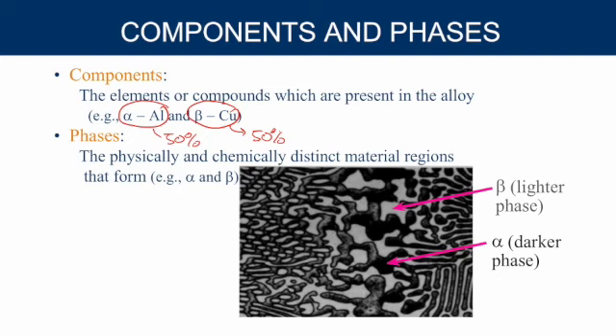So this, we can see the different phases that exist in alloys. This is an actual SEM, electron microscope image of the grains. These are the grains we've talked about before. This would be, say, a room of crystal grains. We have a hallway around the crystal grains, and then we have another room next to it. But here you can see there is a very distinct color difference between those. We have a very light gray, and we have a dark gray system. These are the two phases.